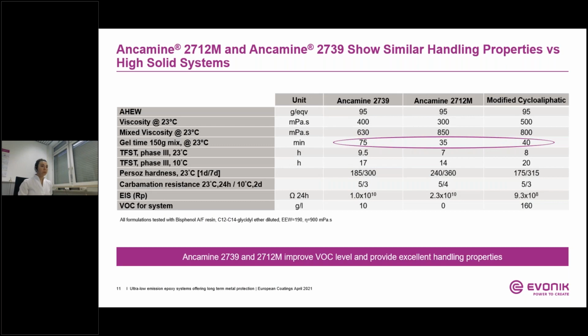Here we will focus on handling properties of Ancamine 2712M and 2739. Both products exhibit very low viscosity, with Ancamine 2739 containing an ultra-low level of plasticizer and Ancamine 2712M being free of any liquid plasticizer. While Ancamine 2739 has been designed to allow for a longer working life, a pot life of 1.25 hours, Ancamine 2712M has been developed to provide coating systems with improved blush and carbamation resistance at lower application temperatures.